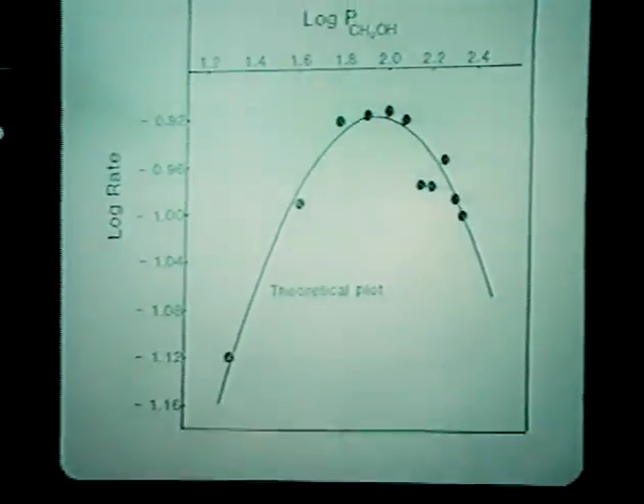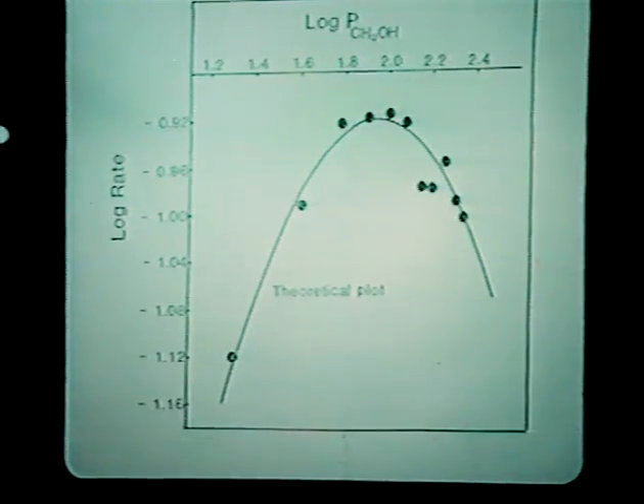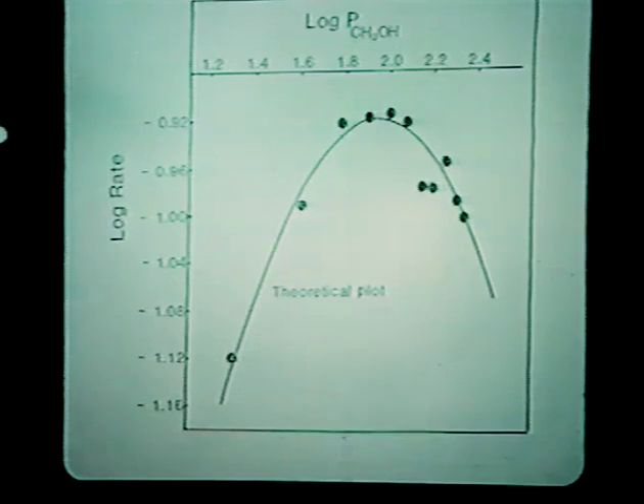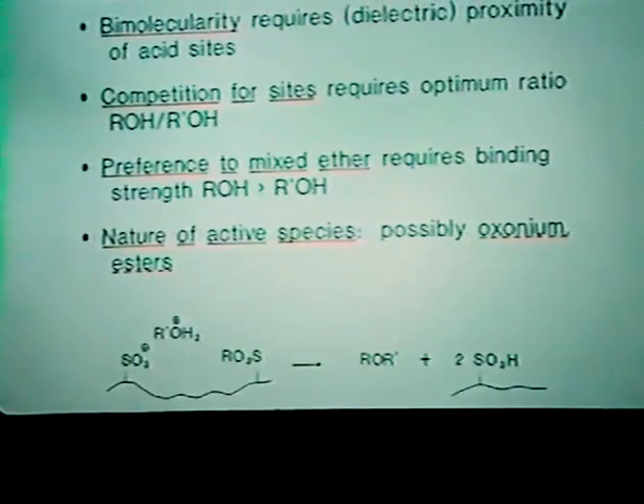If we do the same experiment with isobutanol, keeping methanol constant, we get the same kind of curve, except that it's shifted. We can calculate the equilibrium constant of binding to the acid sites of isobutanol and of methanol, and we find that isobutanol is bonded with an equilibrium constant about 4 times as great as methanol. So we know isobutanol is bonded more strongly than methanol. And this is the key to the selectivity in favor of the mixed ether. But let me first summarize what we know about it and then speculate on the mechanism.